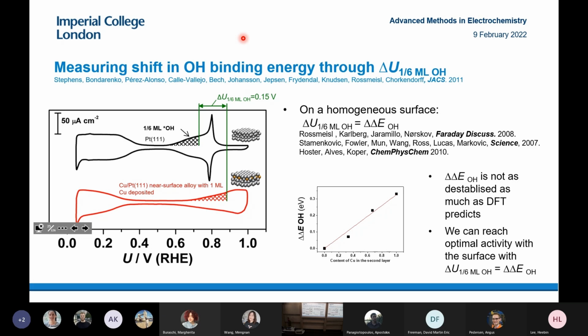But ideally, you go in the middle of the isotherm, so around 1/6 of a monolayer. But it's an approximation, right? So it's not ideal. And what we found, especially when we looked at some of these alloy surfaces, is that the curves were not always parallel. That could be because you have more long range effects, interactions between OH through a water layer, through co-adsorbed water. But it's often better to take a simple model to try and understand it.